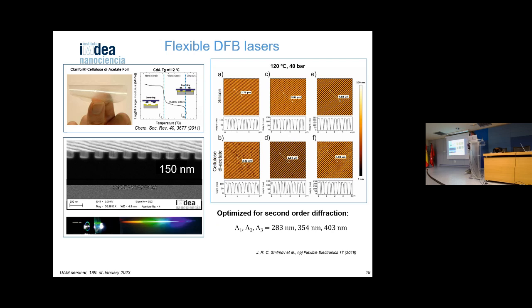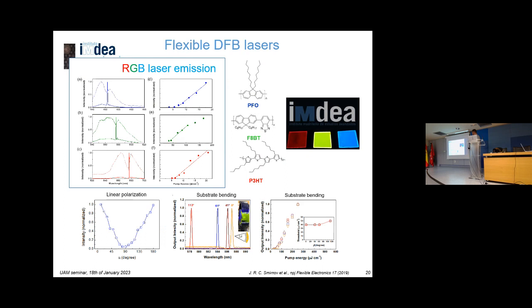We normally work with the second diffraction order because we don't need very short distances between the pitches. Typically we work between 280 to 400 nanometer pitch separations, and these correspond to a picture of such lasers on cellulose acetate.